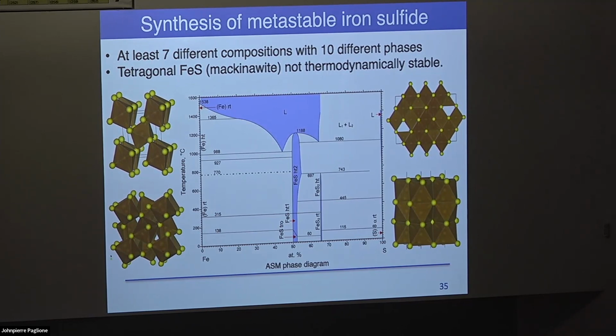So iron selenide is a superconductor, but the sulfide analog is not a thermodynamically stable phase. I know you saw binary phase diagrams on Monday, but if you look at the binary phase diagram for iron and sulfur, the layered iron sulfide structure, which I haven't shown you yet, which is isostructural with iron selenide, does not exist on this thermodynamic phase diagram.